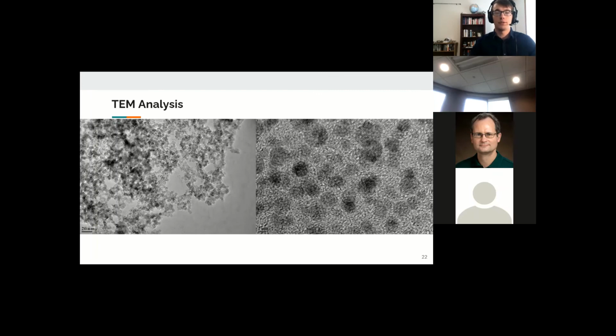The individual particles can be viewed with an electron microscope, and the size and morphology can be directly seen. TEM allows us to peer at individual particles to identify their size, composition, and shape directly. So the particles that we made were spherical and formed in sizes between 1.5 and 4.5 nanometers in diameter typically, depending on the reactor conditions. The main parameter of the synthesis system used to vary size was the carrier gas flow rate and the reactor pressure, because they were the least intertwined variables. The smallest particles were achieved with high flow rates.